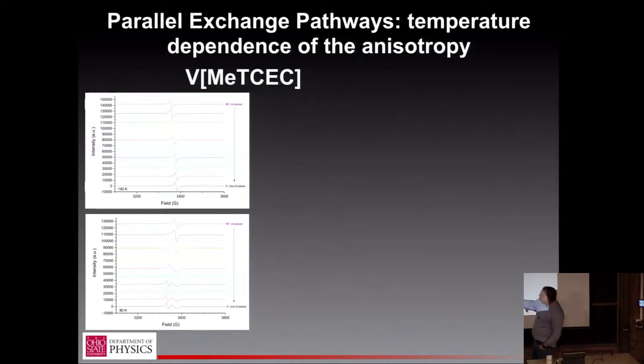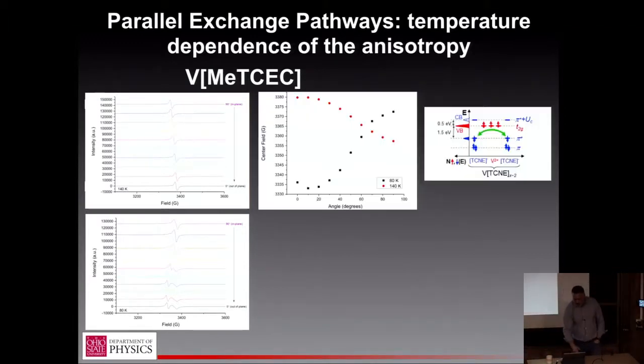And it's kind of hard to see with the naked eye without putting a line on the page, but in fact, these peaks go in different directions. So that's pretty weird. You can see that more easily here, where I'm just showing the central peak as a function of angle. And you see the same kind of sinusoidal shape that we showed for VTCNE, but the phase flips. So this is really interesting and quite surprising.